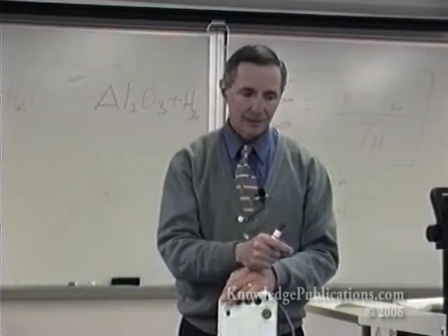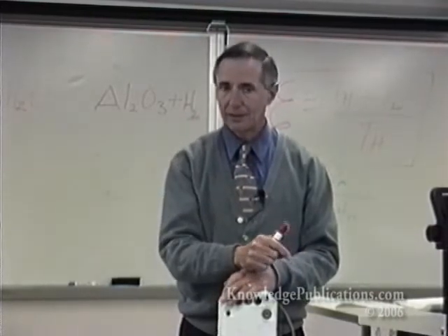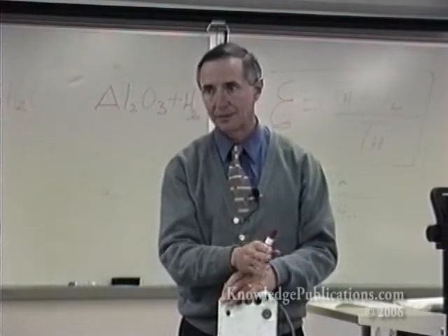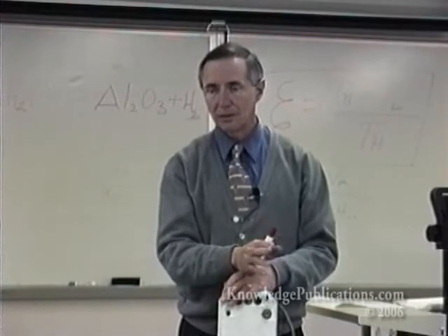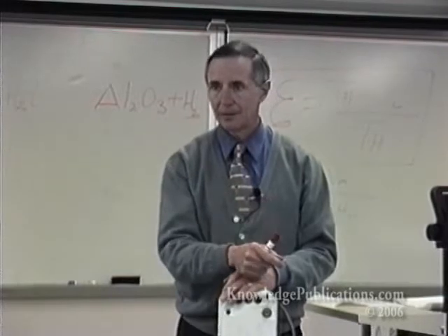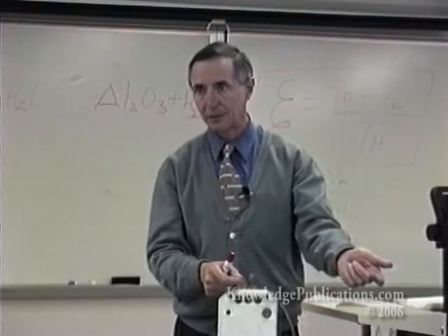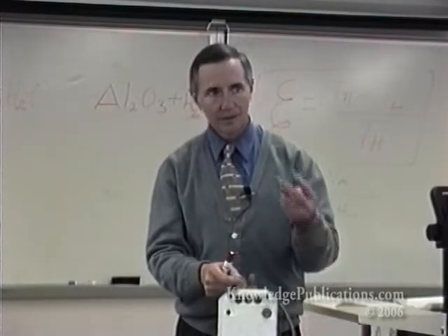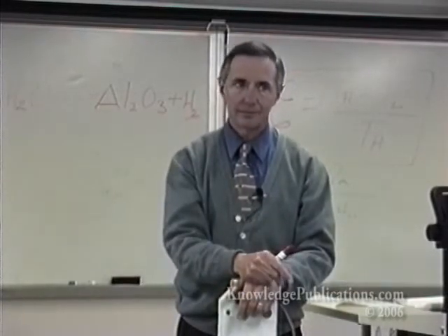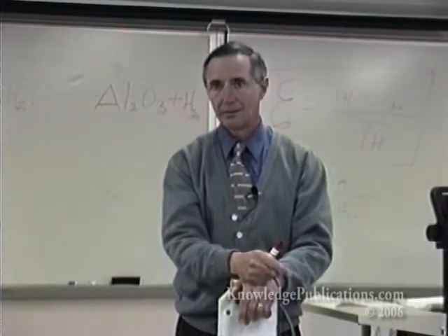My point is this. Based on real world experience, we can hold hydrogen in steel pipelines without question and indefinitely long. So long as, number one, the welders are advised to not use wet rod, so they don't introduce water under an arc which would make it into atomic and ionic hydrogen. Number two, if they think they have hydrogen in a weldment, they should bake it. They should get a torch on and hold it at baking temperatures until it's gone.